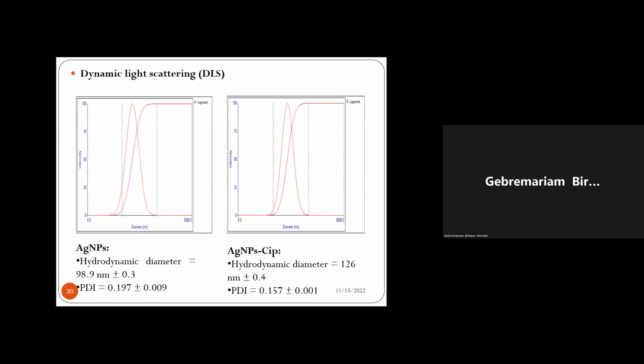We have also measured the size distribution and the hydrodynamic diameter of the synthesized particles and the drug-loaded ciprofloxacin silver nanoparticles. So as you see, the hydrodynamic diameter is 98.9 plus or minus 0.3 nanometers, and the polydispersity index is acceptable.